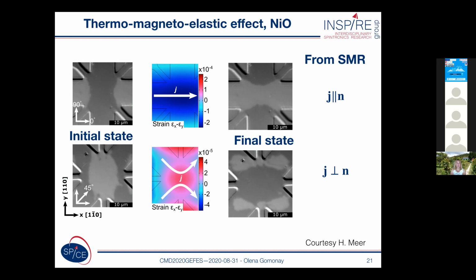In this slide, you can see two different geometries in upper and lower rows. So in the upper row, the current flows straight from left to right electrode, and it creates a strain distribution, which is shown in the center panel by color codes. And this distribution of current, strain, and whatever it is, induces a switching, as shown from left and right panels, to the state in which the Néel vector is parallel to the current direction, which is consistent with both models, the model based on spin-orbit torques and the thermomagnetoelastic mechanism.